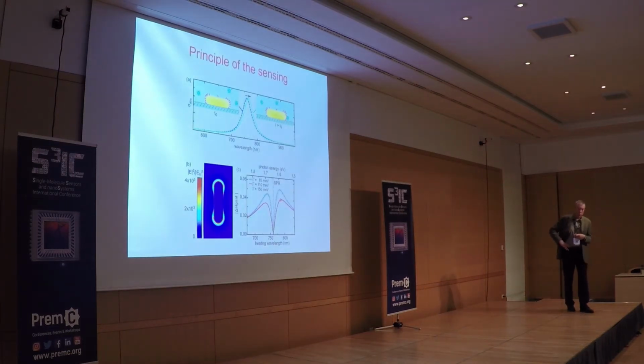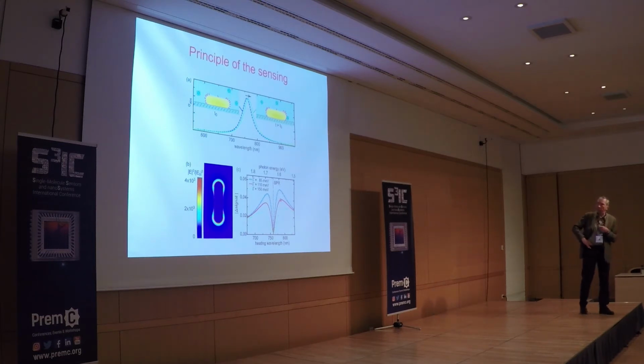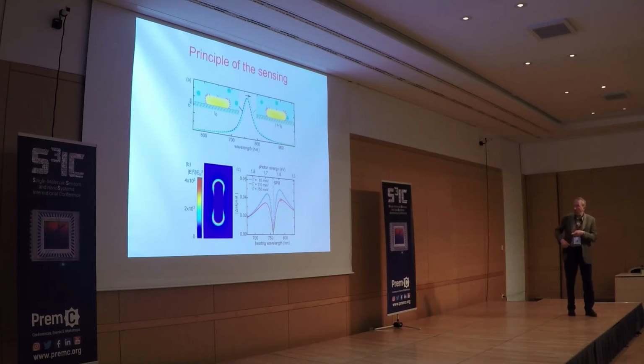So the idea is just to use, again, the plasmon, but this time to detect a change of index of refraction around the particle. So what is going on here? We have functionalized the surface of the gold nanorod with biotin conjugates, and then streptavidin molecules, proteins, will come and bind to this biotin conjugate and change the index of refraction in the vicinity of the tip of the rod. If you change the index of refraction, you bring charges, polarizable entities, and these charges will modify the spring constant of the plasmon. Therefore, the plasmon will feel that and shift a little bit, ever so little, and we can measure that.